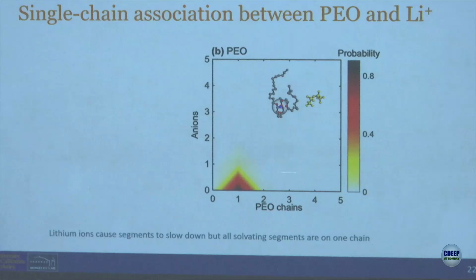Well, this is one way to look at it. These are probabilistic plots, because this is a liquid. And what you see is that typically the anion is far away from the lithium, and you usually have 1 chain and 0 anions. So this peak at 1 and 0 tells you that the typical solvation shell has 1 PEO chain and 0 anions. Of course, you have all kinds of other structures because they are all moving.